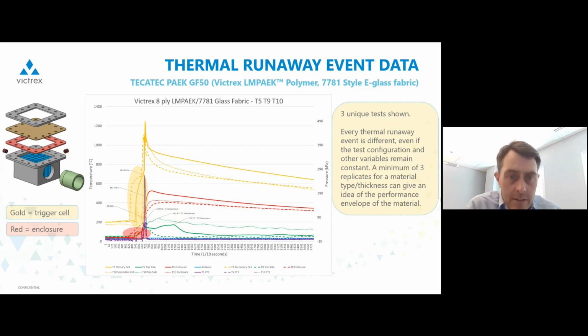And note that in the gold oval there's one particular test, the dash test, that had a funny event going on, and there's a bit of a knee or a bump in the temperature profile there, and you'll see that in the results in a few more slides. But basically, what's happening there is there's a delay between the runaway that's happening from the first trigger battery to the second trigger battery. So, unlike the tests that Petros was just summarizing and describing, with this one you're really trying to generate a bit of an explosion, and in the most controlled way possible. So, it doesn't always go to script, but that's why you do three in a row. Next one.